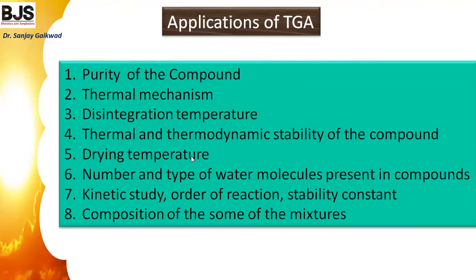The drying temperature — at what temperature adsorbed water is completely removed — can easily be found. The number and type of water molecules present in the compound can be identified. Once the weight loss points and temperatures are known, kinetic studies can be performed, and the order of reaction and stability constant of the compound can be calculated. The composition of a mixture — for example, the percentage of magnesium oxalate versus calcium oxalate — can also be identified.